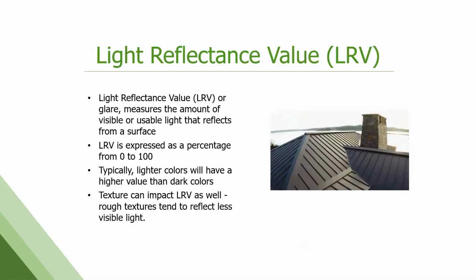So the other reflectance value that comes up a lot is light reflectance. Light reflectance and solar reflectance do get confused with one another quite a bit, but they're very, very different. Solar reflectance is all about that near infrared region, not visible light. Light reflectance value, LRV, is about the visible light that you see off of the surface. We typically call it glare, right? So metal, even painted, can sometimes be quite shiny, so you get a lot of glare and light reflection off of it. It is expressed as a percentage from 0 to 100. Lighter colors will have a higher value than dark colors on average.